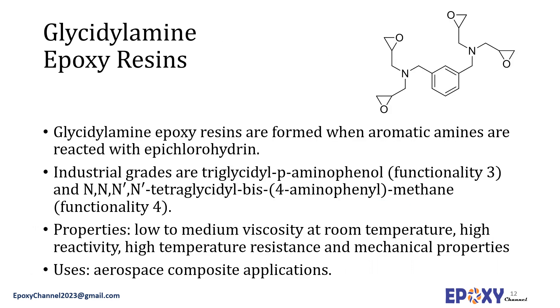Glycidyl amine epoxy resins are higher-functionality epoxies which are formed when aromatic amines are reacted with epichlorohydrin. Important industrial grades are triglycidyl-p-aminophenol with a functionality of 3, and N,N,N',N'-tetraglycidyl-4,4'-methylenedianiline (TGDDM) with a functionality of 4. These resins have low to medium viscosity at room temperature, which makes them easier to process than EPN or ECN resins. This, coupled with high reactivity and high temperature resistance and mechanical properties of the resulting cured networks, makes them important materials for aerospace composite applications.